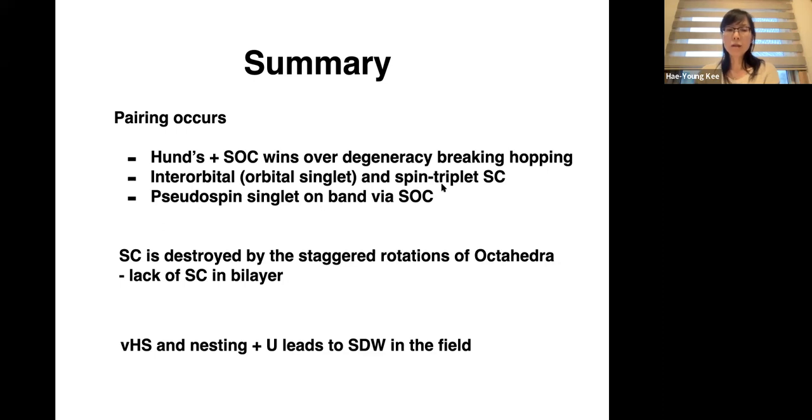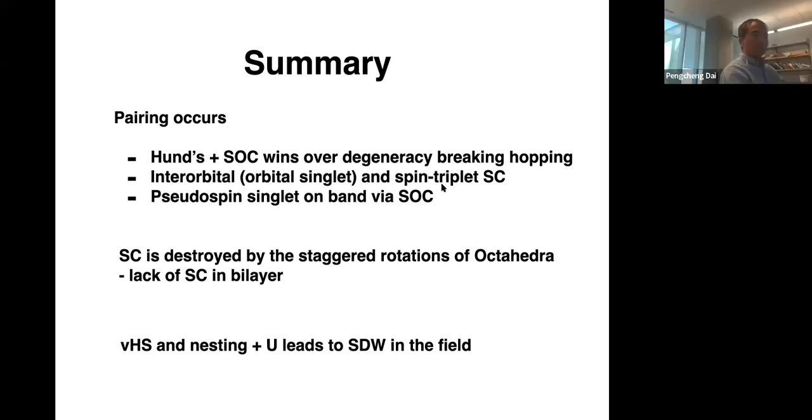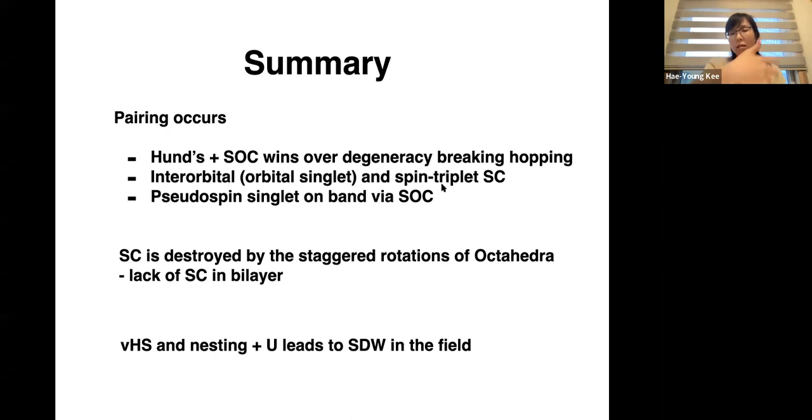Right. That one I will be a little careful about, because yes, you're right. If I was just thinking about a single band with a plus minus, you would have a spin resonance connecting the plus and minus, just like a d-wave, where the neutron comes in and couples directly to a spin. But here there is spin and there is orbital moment. So orbital moment is mixed with spin.